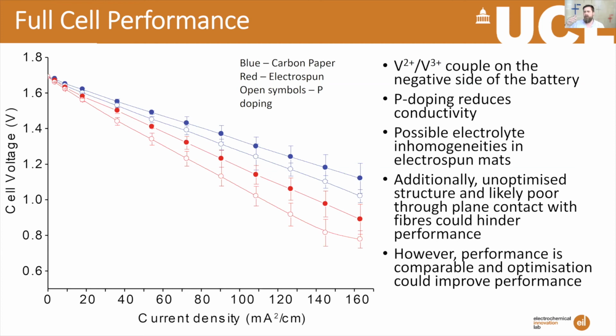Of course, as you get towards the lower states of charge, you have less reactant effectively, a lower proportion of reactant in your electrolyte, and so that becomes much more important. So at lower states of charge, you get the mass transport issues coming in quite earlier. So there's some effect, but largely it's when you approach that limiting case that it's really important. Of course, if you have worse diffusion or worse advection of your material, then you're going to reach that point a lot quicker. So basically, you want to be at the point where the diffusion isn't an issue for as high a current density as you can.